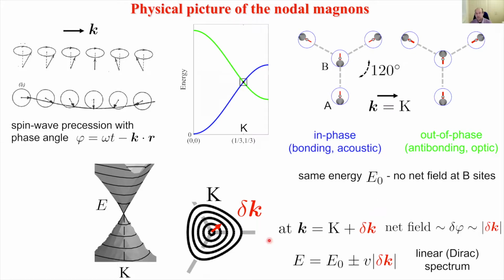So fundamentally, if we go away from the K point in any direction, then there will be a net field, which is proportional in the first approximation to the magnitude of K, and then the energy will depend linearly on K. And this is the essence of the degeneracy and the linear dispersion in the case of the magnons. So at a particular point of the Brillouin zone, there's a cancellation of the interactions between the two sublattices that gives rise to the degeneracy, but moving away, that cancellation is gone, and then we've got a linear dispersion.